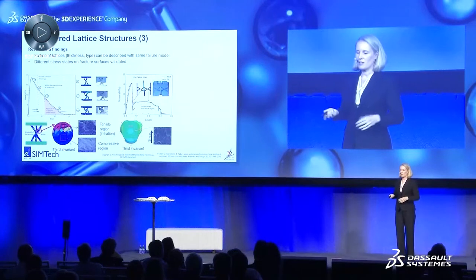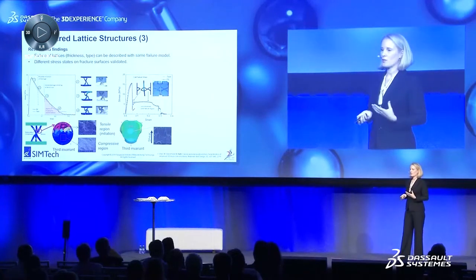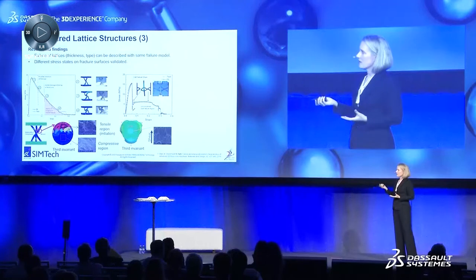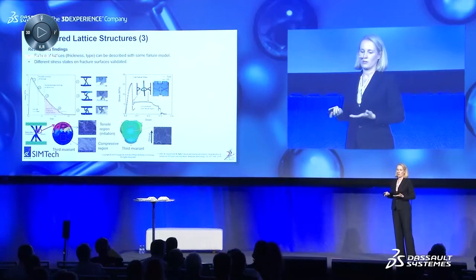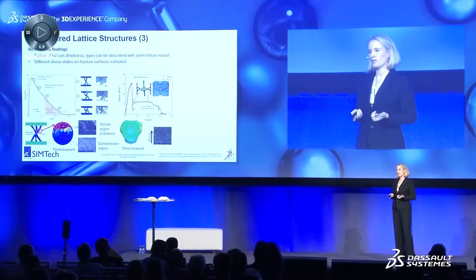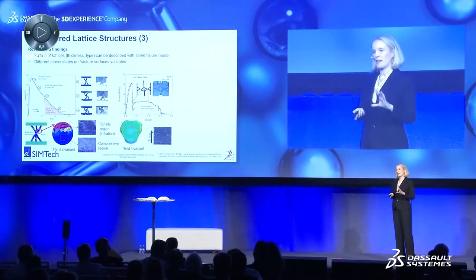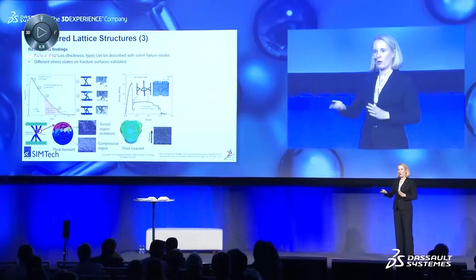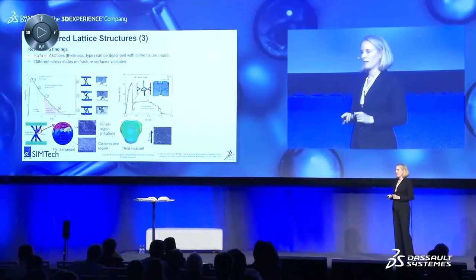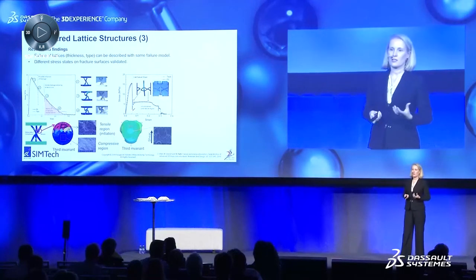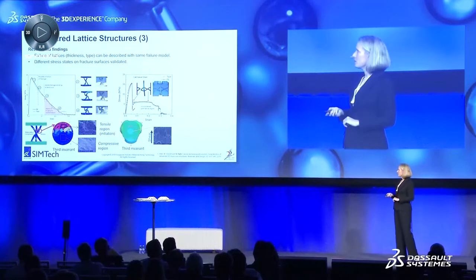So what we could see here is that we have different stress states on fracture surfaces. What we could also see was that the diameter of the lattice plays a role. That's important to consider. And the stress state actually changes if we change the diameter. And therefore, the whole failure might shift because of the triaxiality and the dependence of the failure strain on the triaxial stress state.